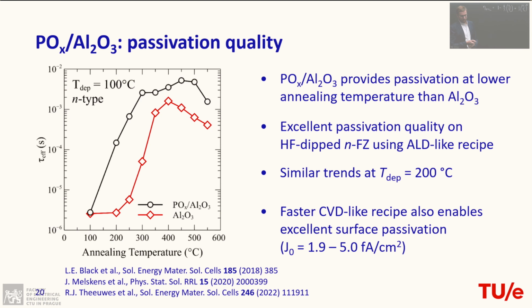The passivation quality for the ALD recipe was then tested for different temperatures, and you see here on the horizontal axis the annealing temperature, which is what you need to do to activate your passivation quality. You, for instance, make it possible for the hydrogen to move from your passivating layer towards the silicon interface, and then your lifetime, as we've seen in the previous presentation also, is a very important parameter for passivation quality as well, although now the time scales are much longer. We talk about milliseconds or more. So with this ALD-like recipe, it was possible already to exceed 1 millisecond, which is quite a good value.